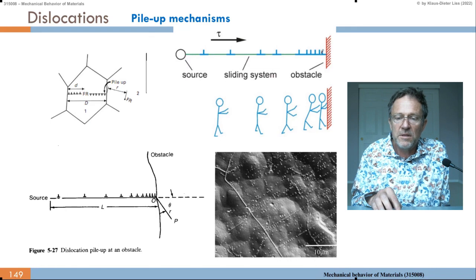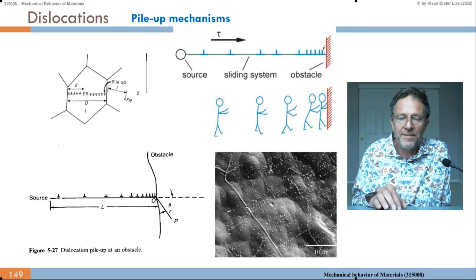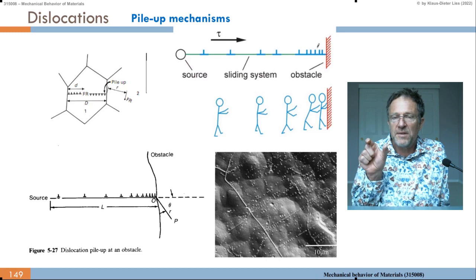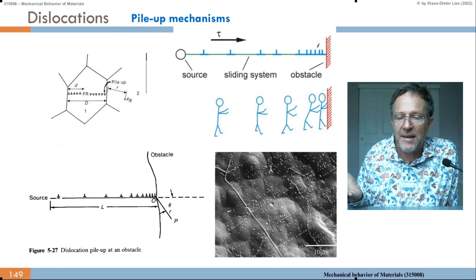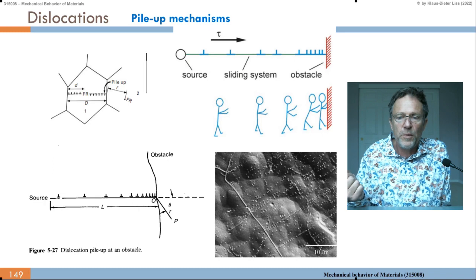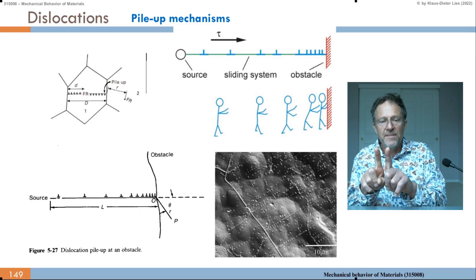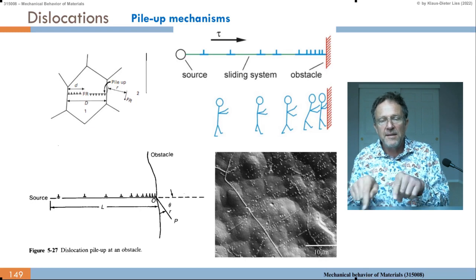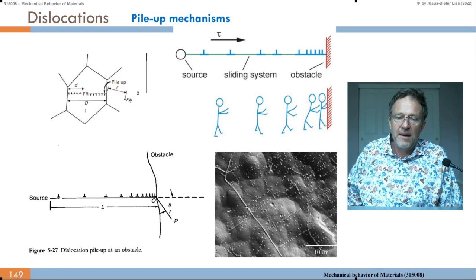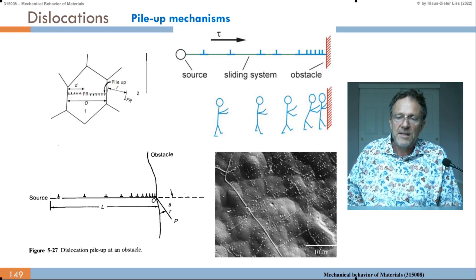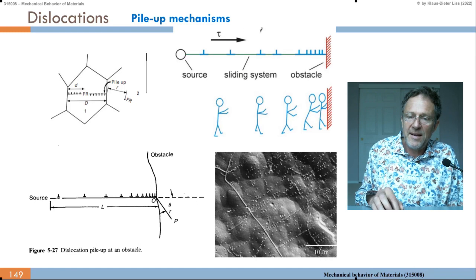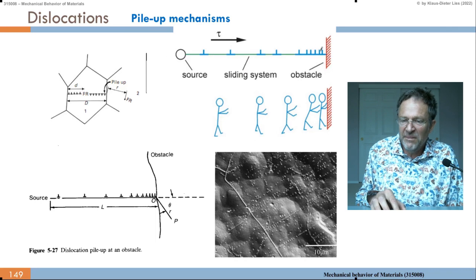If it comes too close, then the energy of the two dislocations becomes larger. If you put one dislocation with double the Burgers vector in, it becomes 4 times larger, as the energy increases with the square of the Burgers vector. So if you put two lattice planes together, then the Burgers vector would be 2b, and the energy would be 4 times the energy for one dislocation. So it stops moving towards the right. If you put the shear stress like this, they all move to the right here, and it piles up behind there.